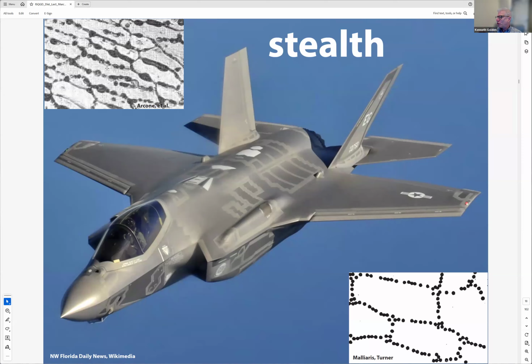And the percolation threshold is then a function of the ratio of the particle sizes. And if you just do a few measurements on the sea ice microstructure and plug it into this percolation theory developed by Kusy, Turner and Malliaris, back in literally the 1970s, then out pops the 5%. But what's so interesting is that these compressed powder composites formed the foundation of so-called stealthy coatings for aircraft, so that aircraft can be cloaked from not light, but radar, microwaves, as we're all aware of.